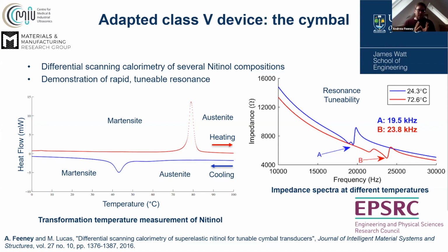I had identified issues with DSC. Residual stresses in the nitinol itself can cause accuracy problems for DSC and nitinol. This was particularly evident for superelastic nitinol. Superelastic nitinol is where the final transition to austenite is just above room temperature. In the context of this DSC plot, that would mean this spike between 70 to 90 would be shifted much lower down, to around 20 to 30 degrees Celsius.